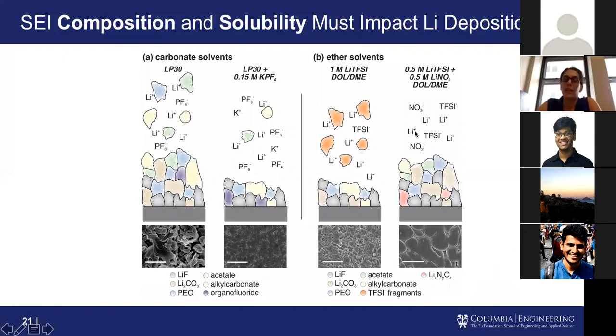So if we have something that is highly conductive to lithium ions, it's basically like having a rapid that's pushing you down the river towards lithium metal, whereas this might be like wading through a mud pool. So in one case, the thick SEI is bad because it's made of stuff that's not conducive to getting you towards the lithium metal surface. But in this case, it's actually helping you get there because what's comprising it here is highly conductive to lithium ions.